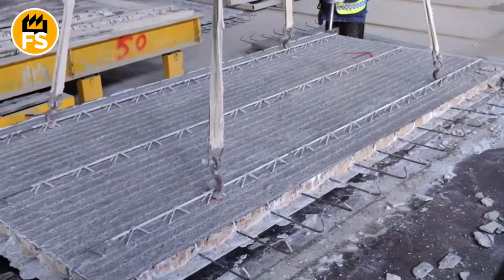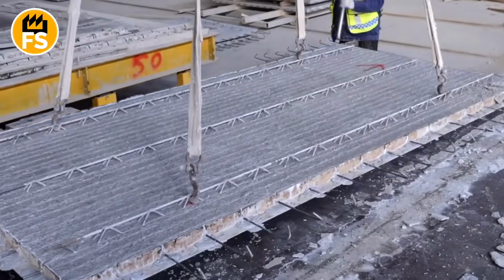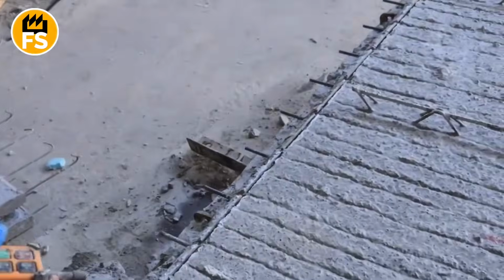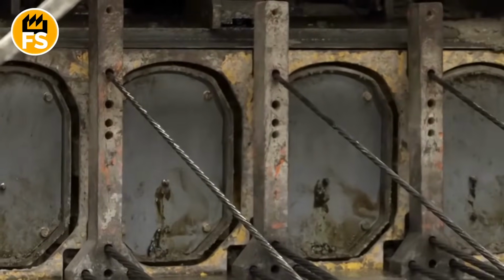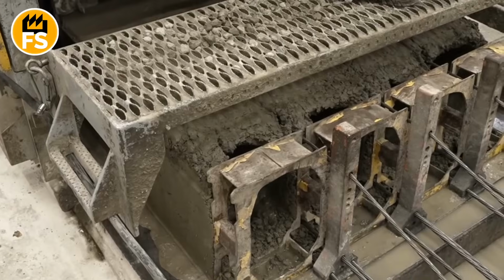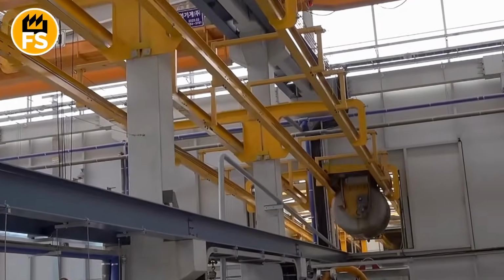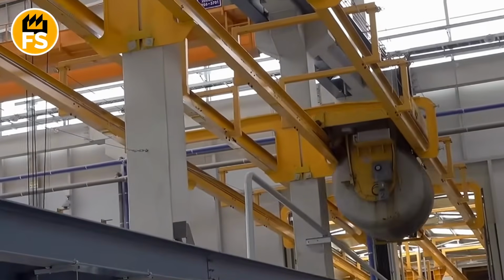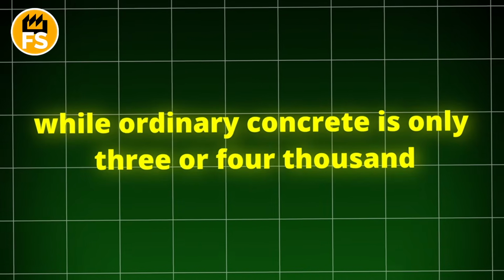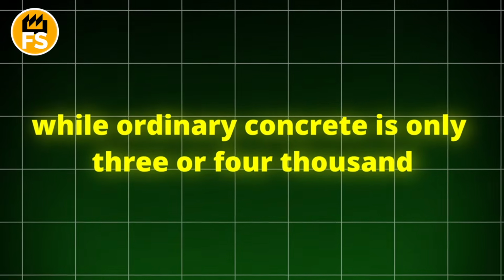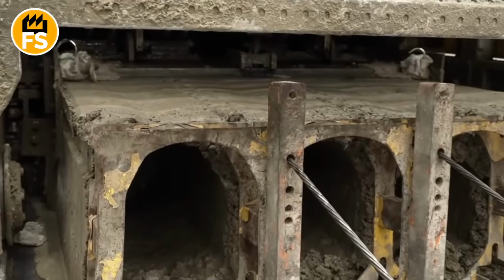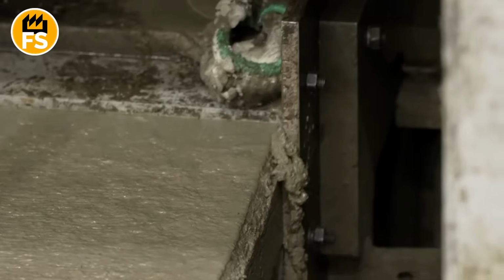But how can such a light slab be strong? The secret is in those tensioned steel muscles. The concrete used in these slabs is not the same as on your sidewalk. This is high-strength concrete that can withstand a pressure of over 8,000 pounds per square inch, while ordinary concrete is only 3,000 or 4,000. And the steel strands inside it are tensioned with such force that they create a constant compressive force in the slab.